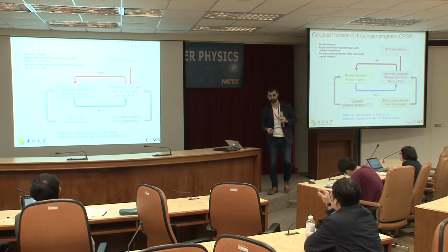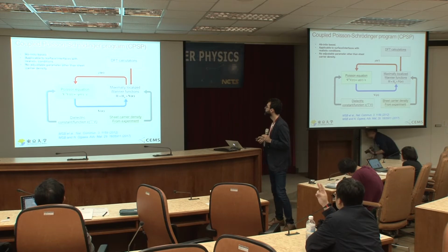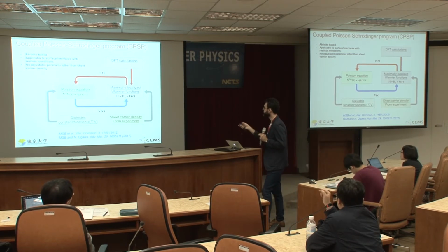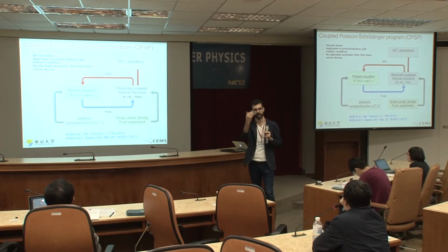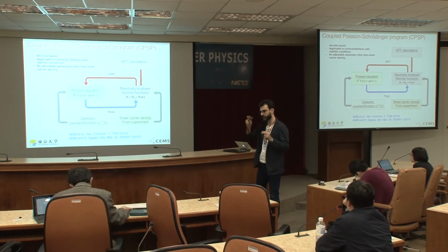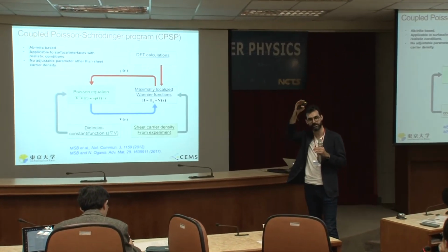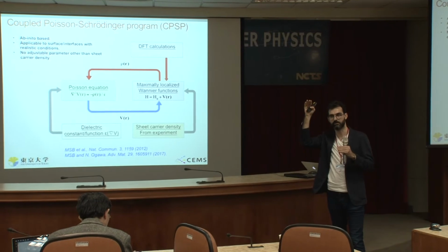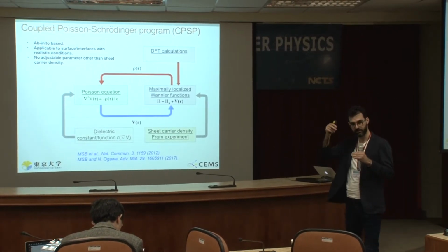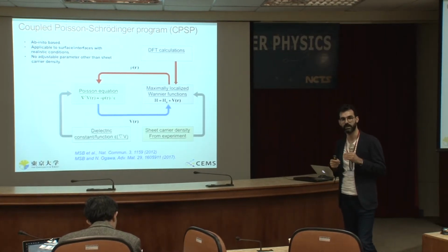Okay. So here in this case, how did you couple with DFT? So we use maximally localized Wannier functions to take the Bloch wave functions from ab initio. So we take those orbitals which are interesting. For example, in the case of this material, we just look at those bands which are related to the conduction and valence band near the Fermi level. So by downfolding those bands, we then can have a simple tight binding Hamiltonian.